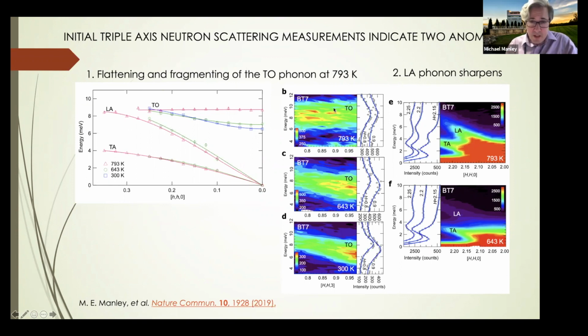There's one thing that's really interesting: this mode goes completely flat, meaning it's no longer propagating. It's the entire phonon, and it also splits up. Another thing that happens, which wasn't expected, and I will explain this in a moment, is that when that branch went flat, the longitudinal acoustic phonon became sharper. That's kind of frustrating, because a sharper phonon means a longer lifetime, which means it's going to increase the thermal conductivity. So we had this thing decrease in one place and increase in another. There's kind of a whack-a-mole thing, but I will explain why that happens in a moment.